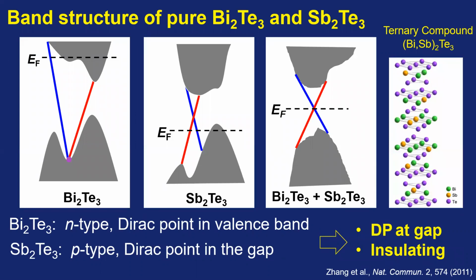This is the band structure of bismuth telluride. This is the conduction band, this is the valence band. In bismuth telluride, the chemical potential usually crosses the conduction band, so the carrier in bismuth telluride is N-type. This is the band structure of antimony telluride. The chemical potential usually crosses the bulk valence band, so the carrier is P-type. So in order to get the intrinsic topological insulator, we mix the bismuth telluride and antimony telluride. It is possible to make the chemical potential cross the Dirac point. So it is possible to tune the chemical potential to approach the charge neutral point.